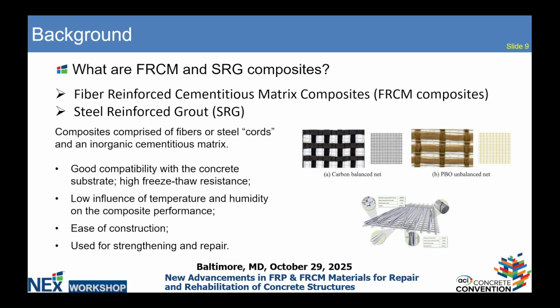And the idea is there are some applications where we're looking for a really good compatibility with the substrate, especially if there is moisture. The inorganic matrix is not as influenced by temperature and humidity as the FRP. It's fairly easy to install. And it can be used for strengthening, but also there are a lot of cases where the concrete cover has been removed because it was damaged, and so it might make sense to have a thick layer of a cementitious mortar with the fibers embedded. So it can also be used for repair.